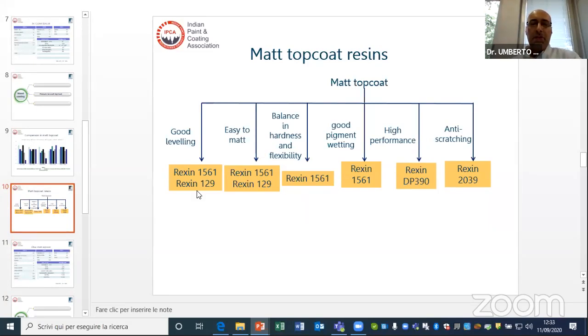Again, we can see the specific properties of the product for good leveling. 1561 is suitable for easy to matt, giving a good matting effect. 1561 is still good. We have a very good balance between surface hardness, a property that is normally required from customers, but also flexibility. The good balance between hardness and flexibility allows us to have a very good surface with very good scratch resistance and also very good resistance to impact that you don't have when you have a too hard surface. We have very good pigment and filler wetting, and so in this way we can formulate the pigmented system.